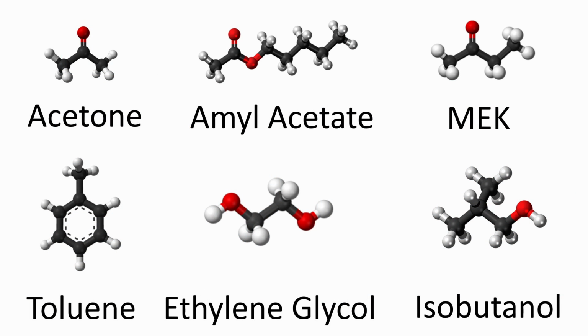Historically, these have been organic solvents like toluene, isobutanol, methyl ethyl ketone, and amyl or butyl acetate. With increasingly strict laws on volatile organic compounds, or VOCs, these are often being reduced in favour of a high proportion of acetone. If a lot of these are ringing bells for you, it's because many of these can also be used as plastic cement. Methyl ethyl ketone, butyl acetate and acetone are all common ingredients of them, and why you can often use lacquer thinner as polystyrene cement, because the polymers of polystyrene are also soluble in them.